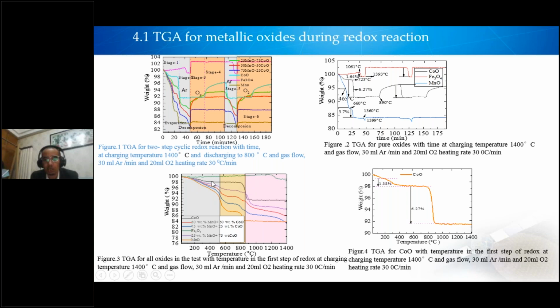Whereas in the first case, for most of the compositions, in this area evaporation starts, and in the second stage, in this area, decomposition, and then a plateau here, at more than 1000 degrees centigrade. This is decomposition, this is the evaporation area. But iron continues constantly without losing its weight. Only at more than 1200 degrees centigrade did iron start to decompose.